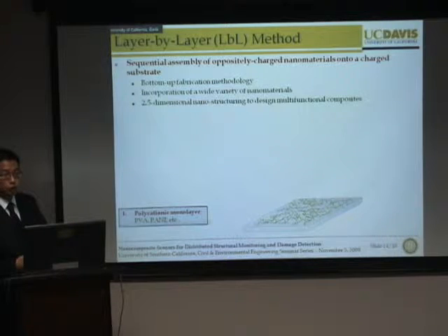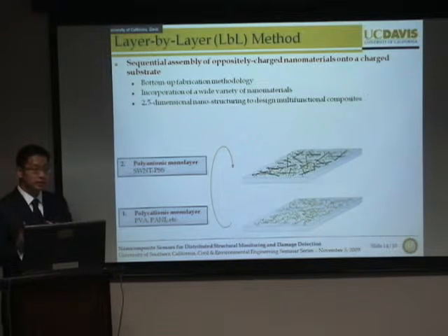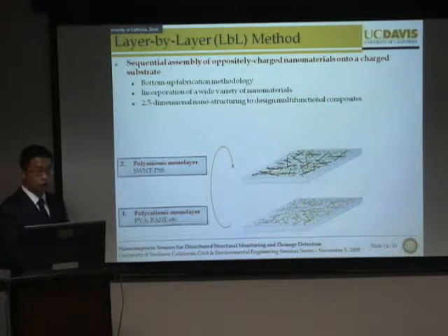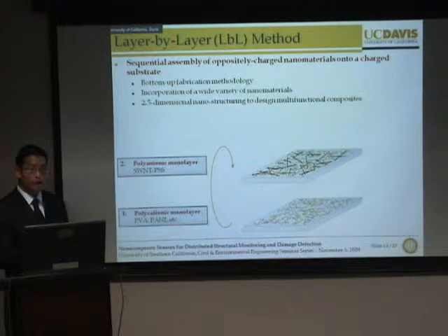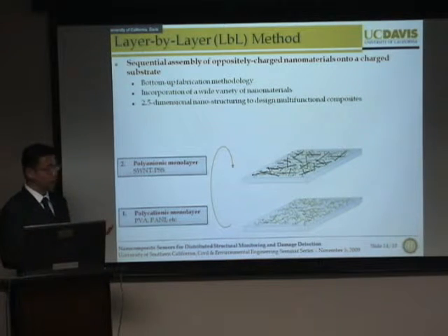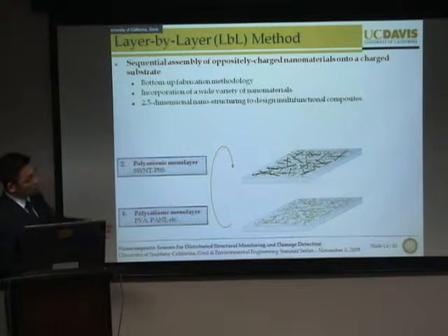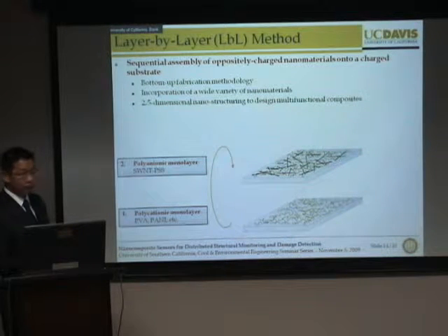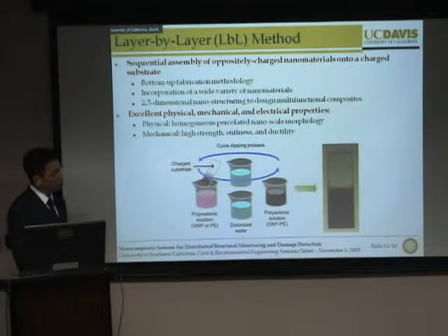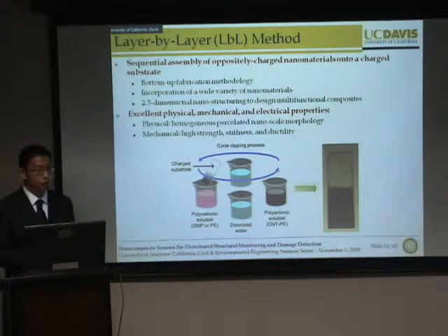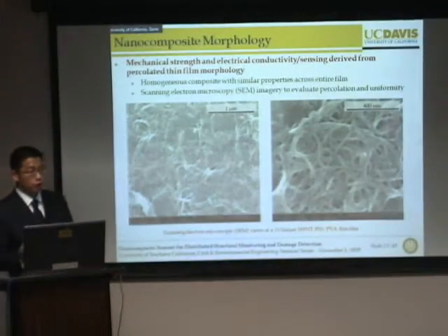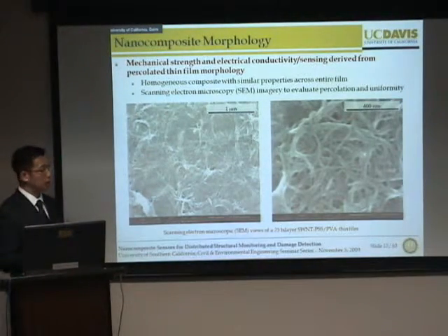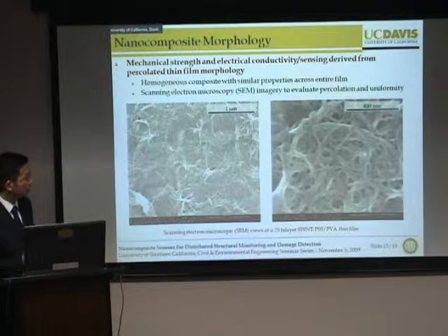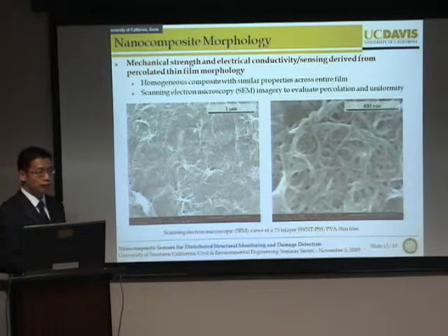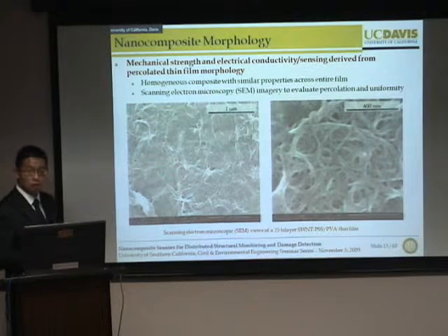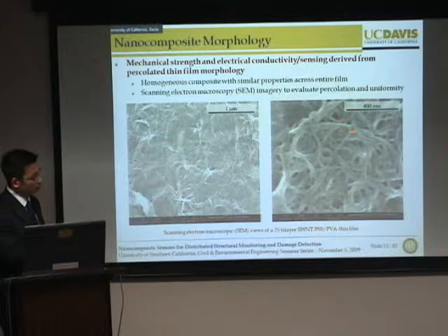Now, upon removal of the substrate and the adsorbed monolayer, we can then dip it into a negatively charged solution, which in this case is single-wall carbon nanotubes dispersed in a PSS, or polysodium styrene sulfonate, solution. By repeating this process 50 or 100 times, we can deposit a very uniform film onto a glass substrate, for example. If we utilize scanning electron microscopy to explore the micro and nano morphology of this material, we do see a highly dense and percolated deposition of only individual and small bundles of nanotubes, as shown by these white lines, or in this zoomed-in picture.